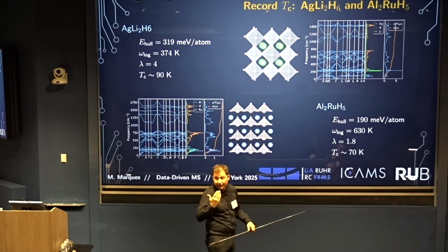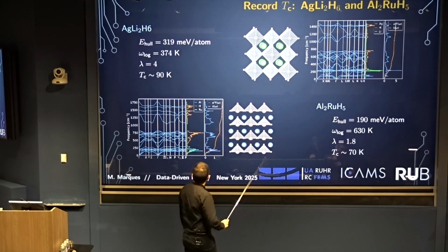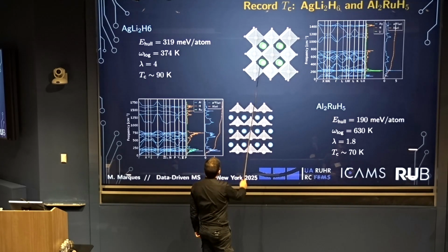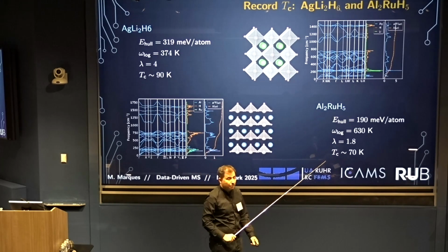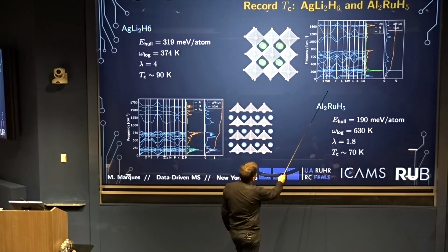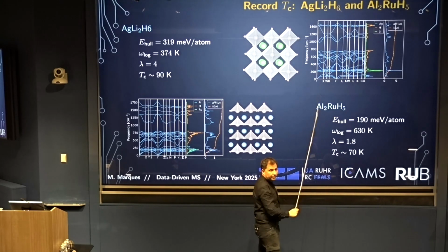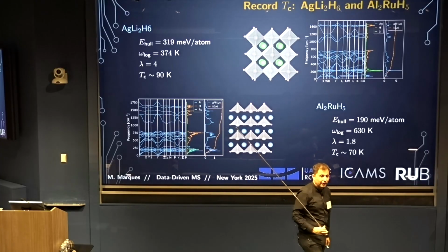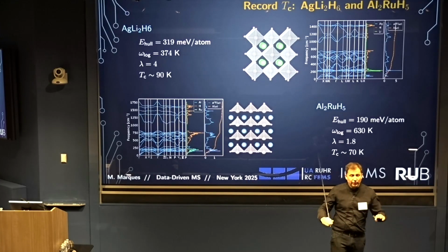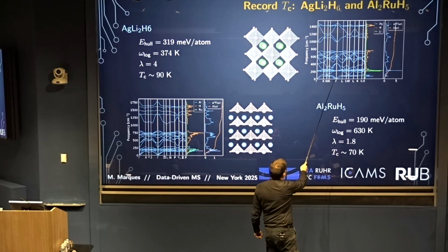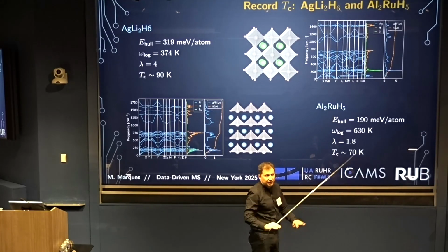Hydrides are the ones with the highest TC, for reasons we all know. This is one of the ones that we have with the highest TC. Perfectly, well, the phonons are a bit imaginary here, but Ion fixed it by using anharmonic effects. So if you put in anharmonicity, these small imaginary things that you see here get immediately cured.